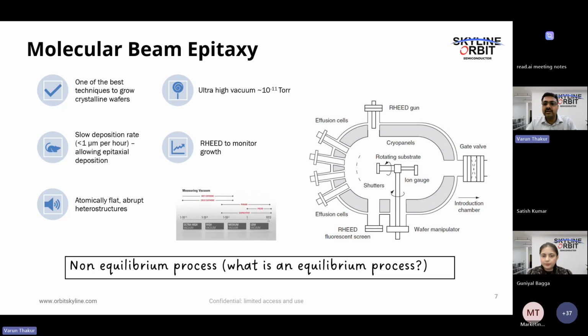Now, one of the most important things to understand is what this ultra high vacuum is useful for. Ultra high vacuum helps in reducing the contamination of the chamber, so the material will not hit against any air molecule or any other moiety before falling onto the substrate. This gives us an ultra pure crystalline film, which eventually, when we make a device on top of it, will be of higher quality. So the devices will have better performance. We usually get atomically flat and abrupt heterostructures. There is no intermixing at the interface. So eventually, it all helps us in giving a better quality device.